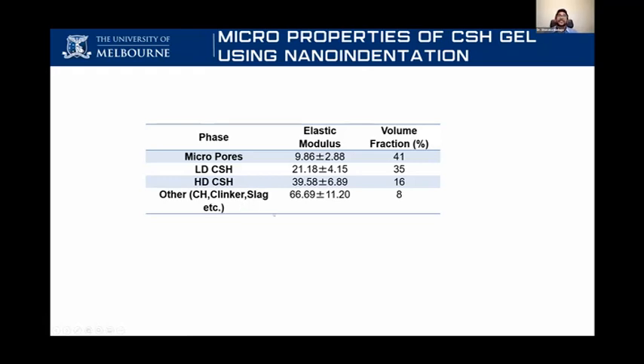So this clearly shows what is actually contributing a lot to the concrete strength, and what reduces the strength and the elastic modulus of the high strength concrete. Actually, the weakest point is the reacted cement. And the pores are what cause the problem in concrete, not the cement. The unreacted cement is really good. It increased the strength and also increased the elastic modulus. Calcium hydroxide is also the same, it's very strong. Unreacted slag is also the same. So in high strength concrete, because of the lower water to binder ratio, most of the cementitious particles don't react.